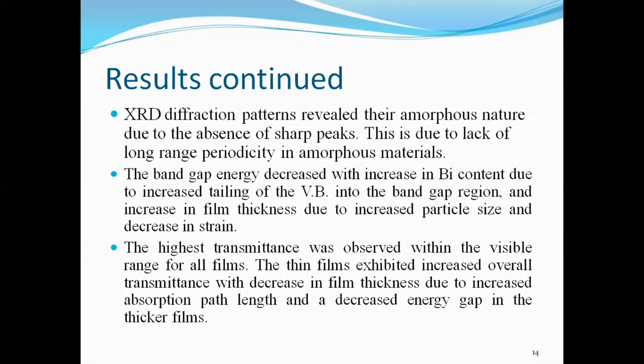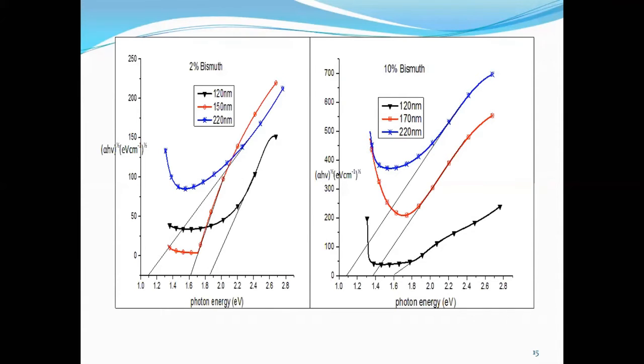At the same time, the band gap energy also decreased with increase in film thickness. And this was attributed to the increase in particle size and decrease in strain. Allow me to go to the slide where I have the diagram for band gap. You can see